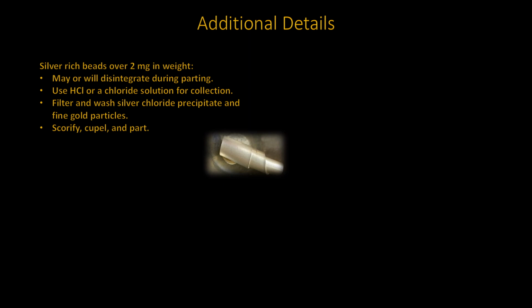Another type of chloride solution, such as sodium chloride, may be used. The silver chloride will actually precipitate and collect those fine gold particles. They can then be filtered off and the paper ignited, scorified with lead, then cupelled. The resulting bead may then be parted.